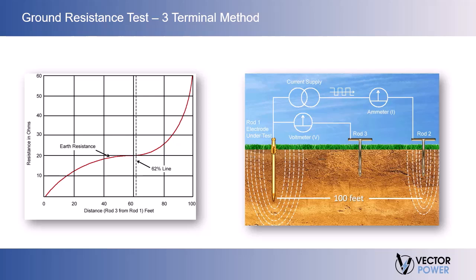Now, let's say that rod 1 is our electrode under test. From a typical earth resistance curve, such as the one shown, what is the resistance of the earth rod? We can call rod 2 our current reference probe and rod 3 our potential reference probe. The correct resistance is usually obtained if a potential reference is placed at a distance from the center of the earth electrode under test at about 62% of the distance between the earth electrode under test and the current reference probe. For example, the distance from the earth electrode to the current reference probe is 100 feet. Taking 62% of this distance, we get 62 feet. The resistance for this distance is 20 ohms. This is the measured resistance of the electrode under test.